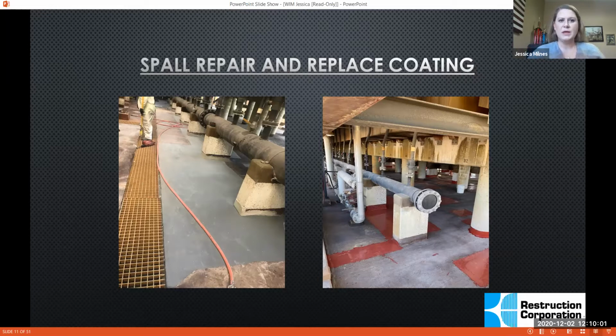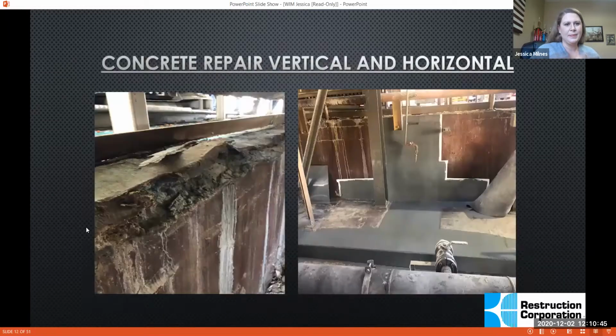So it's not 100%, but it also has a really fast cure time. So we're not sitting and waiting 28 plus days in order to cover over this concrete to protect it. It begins to harden immediately, it has a fast cure time, and we're able to go over it really quickly, protecting it even further. The other good part about a concrete like this, as opposed to using a ready mix in an environment like this, is that if there is a failure in the coating, this concrete itself is sulfuric acid resistant, meaning it's going to help keep the acid from getting into the ground or into whatever substrate is underneath it.